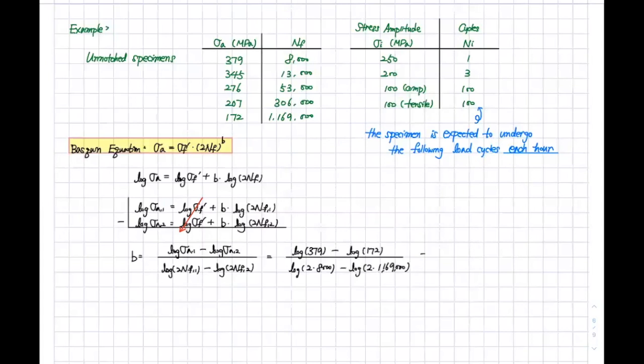Okay, and when you calculate, this number is 0.159. A little different, as you know, from the previous examples, but anyway it doesn't matter. What is the material property? We can insert any values. So let's insert the first one, 379 megapascals, into the Basquin equation: sigma F prime times 2 times 8,000 to the power negative 0.159. Then you calculate using a calculator, and you get sigma F prime equals